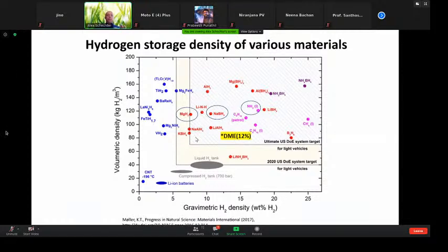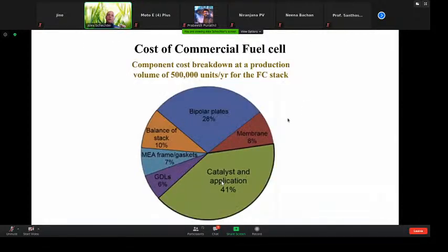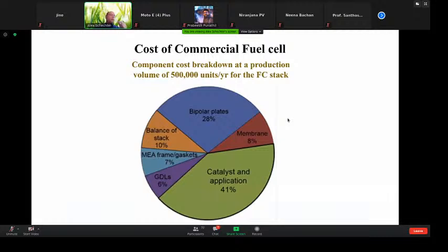The second problem is the cost of the fuel cell. This is a breakdown of the cost. As you can see, the major expense is coming from the catalyst itself. If you remember, we have catalysts at both electrodes. Now, most of the catalyst goes to the oxygen and not to the hydrogen. Hydrogen is a quite fast reaction, but oxygen is a very slow reaction, as I will mention in a minute. But the problem is that the catalyst is made of platinum in this type of fuel cell.